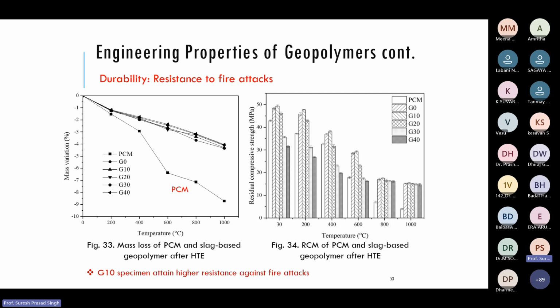The procedure we adopted is like this. The 28 days cured samples, from the ambient temperature of around 30 degrees Celsius, are gradually raised at 5 degrees centigrade per minute till they reach 200, 400, 600 and so on. Once reached, the samples are subjected to high temperature exposure for 1 hour. Then we gradually reduced the temperature to ambient room temperature. Then we find out how much mass loss there is and what the residual strength is. You can see that for conventional Portland cement mortar the mass loss is about 9%, but here it is 1 to 2% mass loss.